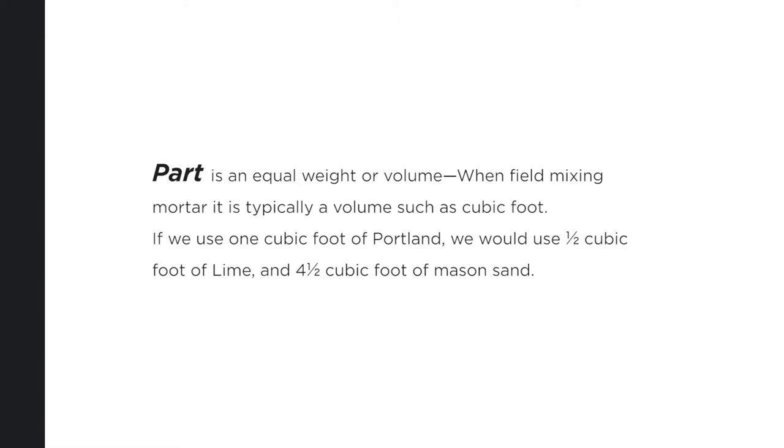When using the term part, a part is an equal weight or volume. When field mixing mortar, it is typically a volume such as a cubic foot. If we use 1 cubic foot of Portland, we would use 1/2 cubic foot of lime and 4.5 cubic foot of mason sand.